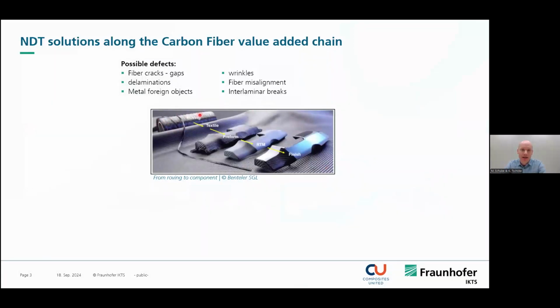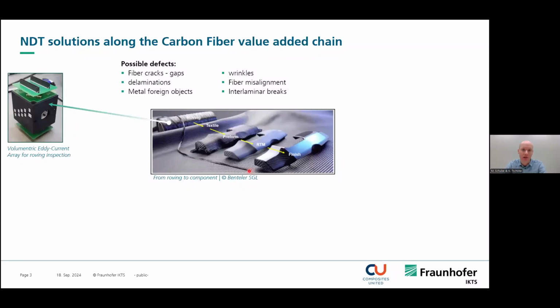Here we see the stages of how to manufacture a CFRP component. It starts at the roving, then goes over the textile, the preform, the RTM, and then the finished component. And we want to inspect the whole carbon fiber value-added chain. This is possible with NDT technique based on high-frequency eddy current technology.